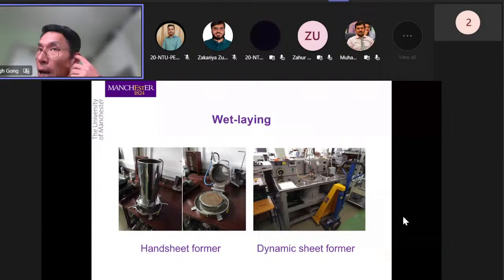In our university, we try to use wet processing, wet non-wovens, essentially wet laying, which is a very common non-woven making process. For example, we use that to make wet wipes. A lot of these baby diapers are made using the wet process as well, and filter materials. Essentially, it's based on the paper making facility. We had two different types of machines. One is the hand sheet former, essentially a hand machine, mixing the carbon fiber in fluid, and then you draw it onto a filter to form the hand sheet.